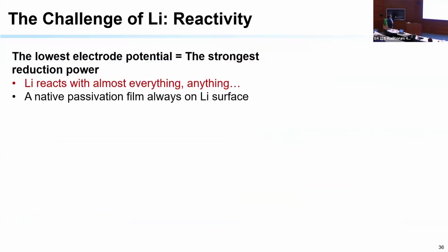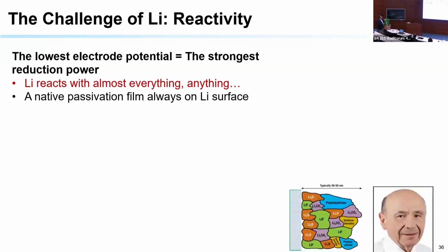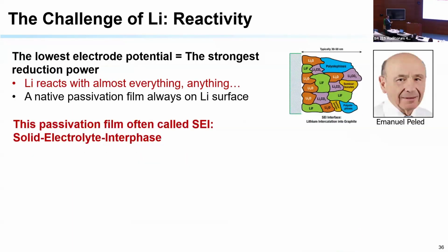So this means that the lithium, because of this redox potential, is one of the most reactive elements. It reacts with almost everything. And when it does react, it forms these surface layers. There's a lot of study on them. They are complicated. You see the lithium metal right there, okay? After the electrolyte reacts with the lithium metal, you form nearly a mess over there. And people have spent many years studying this layer, and they call it the solid electrolyte interface, SEI. So you're going to hear me saying SEI.